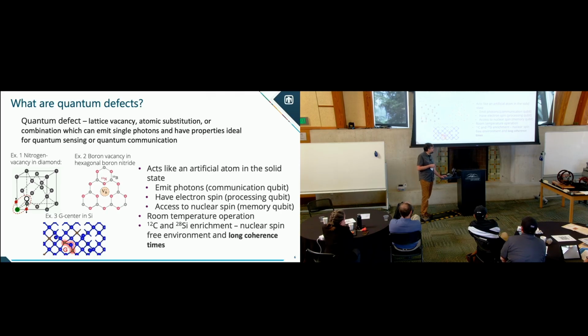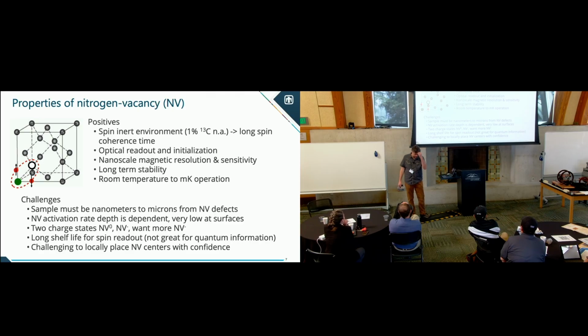All right, so let's talk a little bit more specifically about the nitrogen vacancy in diamond. In general, even without isotopic enrichment, carbon, which is the only constituent of diamond, only has 1% carbon-13 natural abundance. And we work with groups that do isotopic enrichment with CVD growth on top of the diamond, so you can get very low carbon-13 content and very long coherence times. You have access to optical readout and initialization, so it can be optically controlled, which all of this gives you nanoscale magnetic resolution and sensitivity.